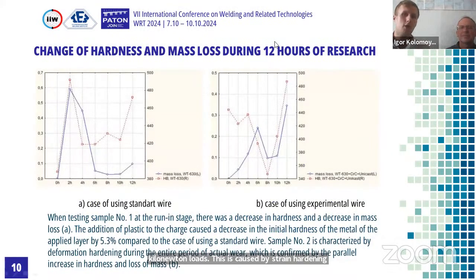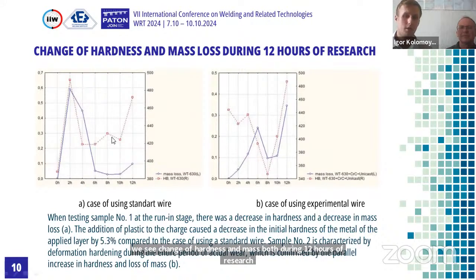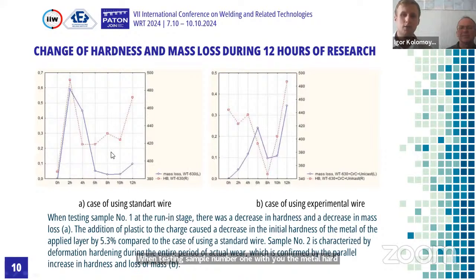Here we see the change of hardness and mass loss during 12 hours of research. When testing sample number 1 with the metal hard face with the standard wire at the running stage, there was a decrease of hardness and decrease of mass loss. The addition of plastic to the charge caused a decrease of initial hardness of the metal by 5.3% compared to the case of using the standard wire.